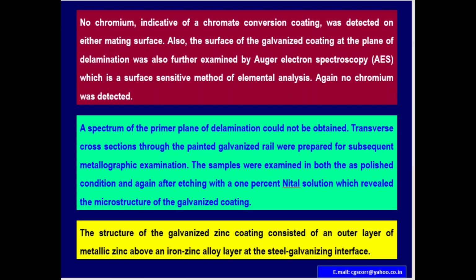Also, the surface of the galvanized coating at the plane of delamination was further examined by Auger electron spectroscopy, which is a surface sensitive method of elemental analysis. Again, no chromium was detected. A spectrum of the primer plane of delamination could not be obtained.